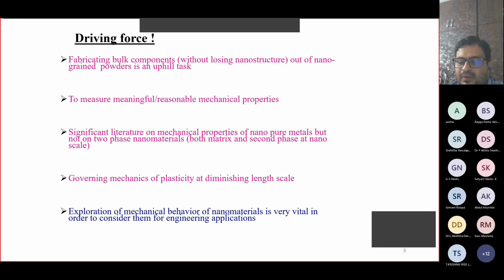Also, when you diminish the length scale, for example, from 100 nanometers to close to 10 nanometers of grain diameter, you can in principle estimate how many atoms are sitting in that grain. The reason is that the interatomic distance, in other words your lattice constant, is about 3 to 5 angstroms for most crystalline materials.